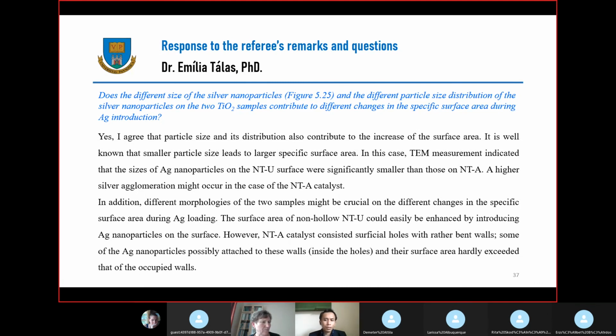In the NTA, it's about 100 or 150 nanometers, but in the NTU catalyst, some of them are even smaller, from 50 nanometers. So a higher silver agglomeration may occur in the NTA catalyst. However, in addition, the different morphology of the two samples may be crucial for the different change of the specific surface area during the silver modification. The surface area of the non-hollow NT-U structure could easily be enhanced by introducing silver nanoparticles on the surface, maybe with the smaller particle size and also distribution.